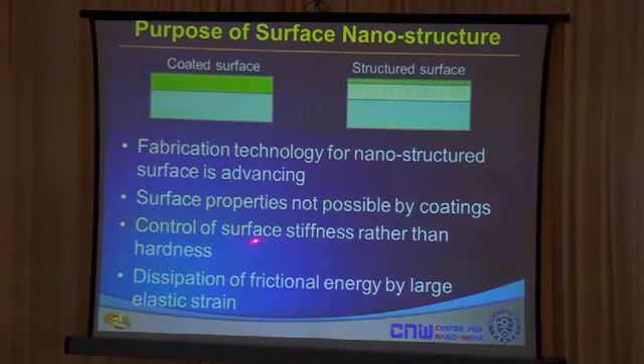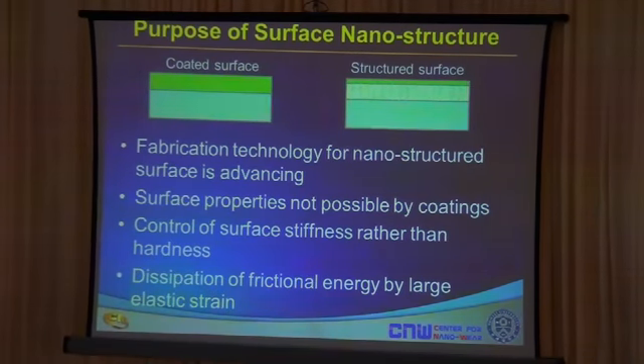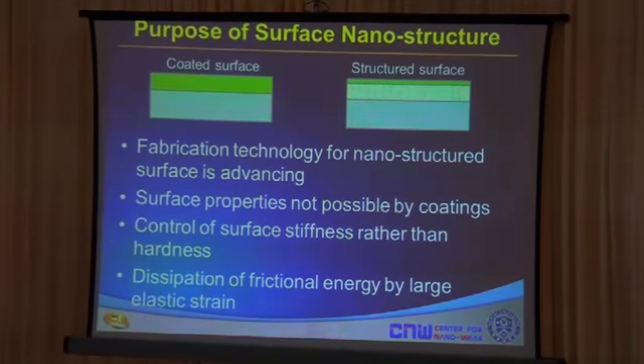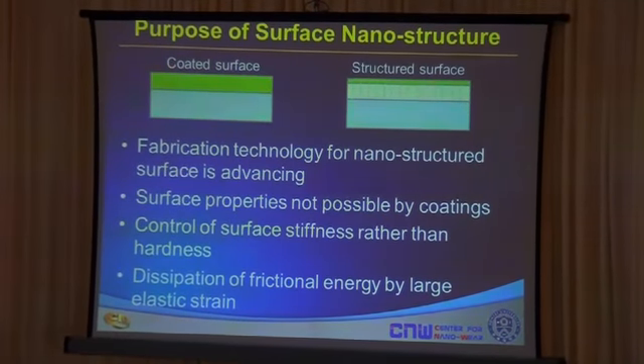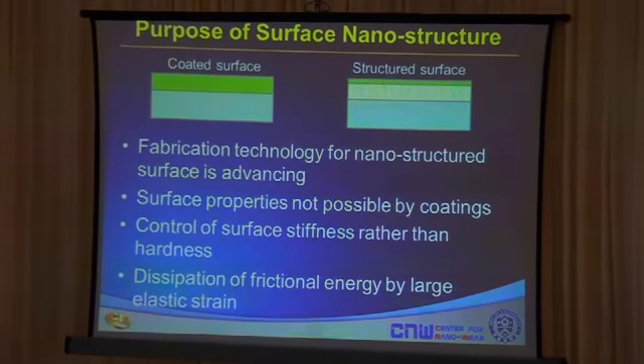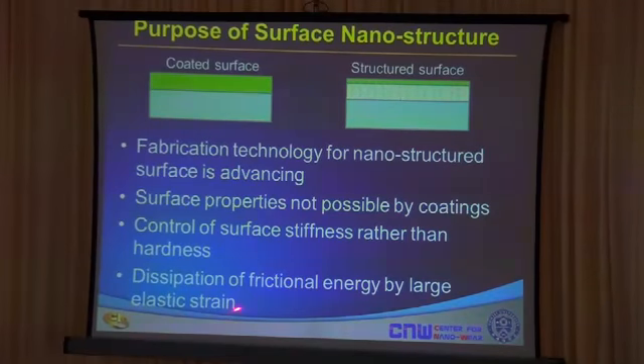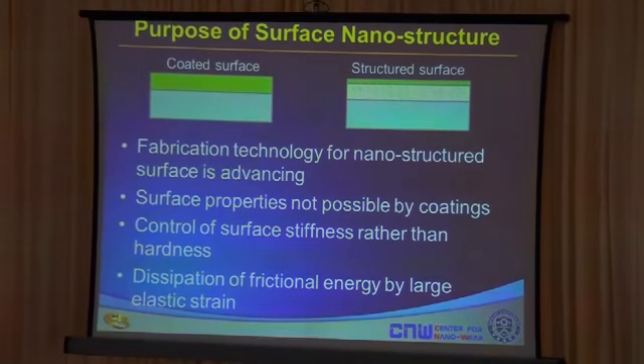And the concept here is to control surface stiffness rather than hardness. So we would like to change the paradigm from making the surface as hard as possible to controlling the stiffness to optimize the pressure at the interface to reduce friction and wear. So ultimately, by achieving large elastic strain, we hope to dissipate the frictional energy that would otherwise be used to permanently deform the surface to create wear.